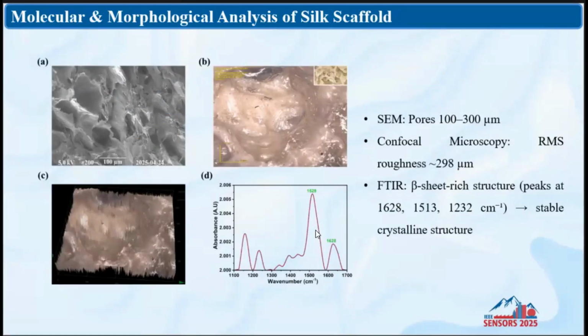Okay, and then after that, we confirmed from the SEM that the pore size is 100 to 300 micrometer, and from the confocal microscopy, we confirmed a 298 micrometer RMS value.